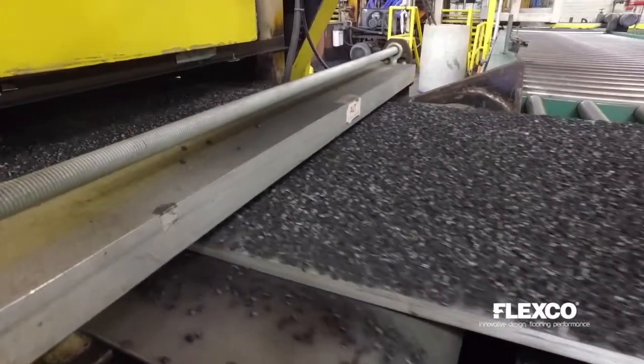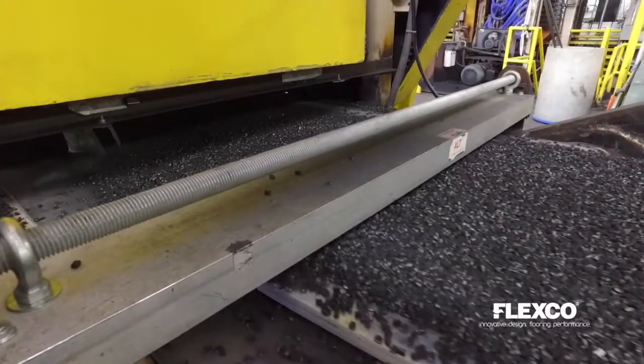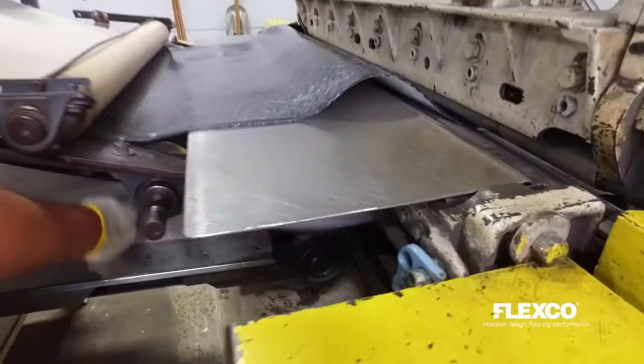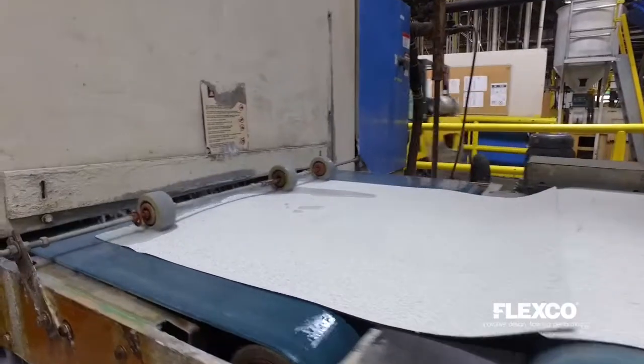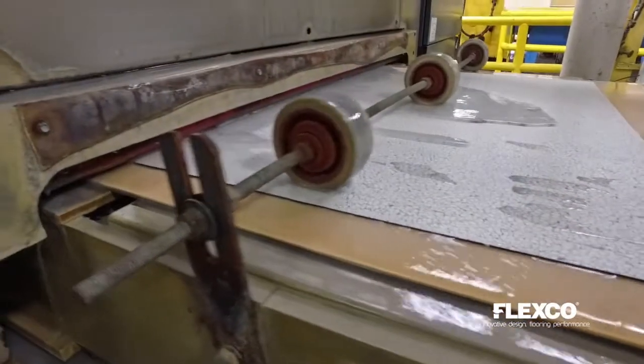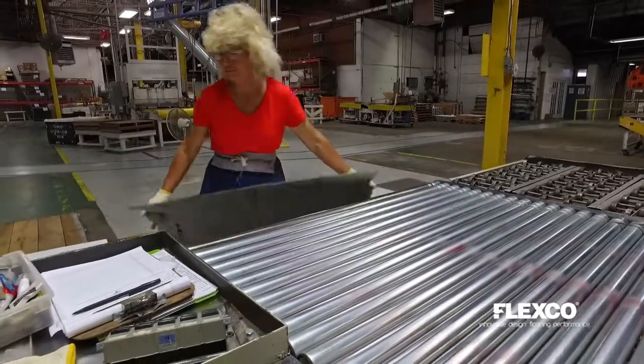Vinyl chips are carefully coated with a proprietary black conductive material and loaded onto mold boards in preparation for molding. After pressing, the tiles are cooled and trimmed. These thick slabs are then split into multiple layers according to the thickness specified. The slabs are then sanded to the precise gauge required. Next, the surface of the tiles are polished utilizing a wet sanding process. Each slab is then inspected prior to heading to the next process.